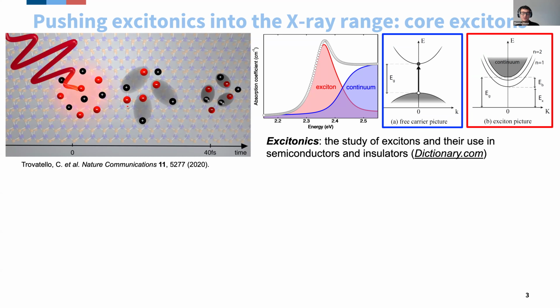To know if a semiconductor you are working on actually has excitonic resonances or not, you can look at, for instance, the optical absorption spectrum. I'm showing an example here on the right, an optical absorption onset made of a very prominent resonance followed by a continuum of absorption. And the exciton, the particle I'm talking about here, is the one that forms this prominent resonance below the bandgap of the semiconductor. So you actually need 2